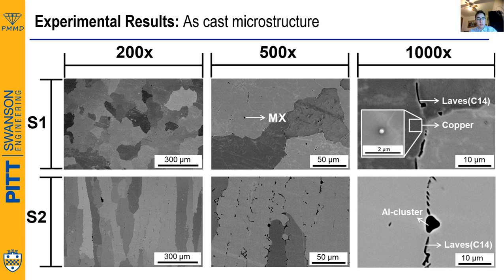These latter ones are hard to find because of their low volume fraction, but they are easy to identify in the sense that the squarish morphology corresponds to these titanium carbides. Strangely though, these are not the only features in the as-cast microstructure. As you can see in the top right corner, these as-cast samples show a non-well homogenized microstructure, exemplified by the fact that we found some copper spheres that were not fully dissolved into the matrix.